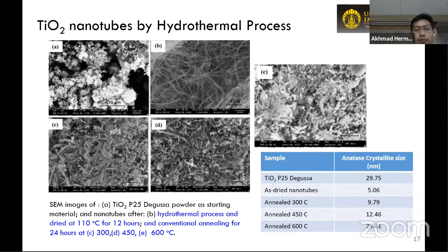And when we improve the crystallinity by calcination at 300 degrees Celsius, the crystallite size improves to about 9 or 10 nanometers, and increasing the calcination temperature further to 450 degrees Celsius and 600 degrees Celsius, the crystallite size has been significantly improved. But again, the growth of the crystallite size, of course, has made the structure collapse. That's actually the challenge we have with conventional calcination or annealing. Next slide, please.